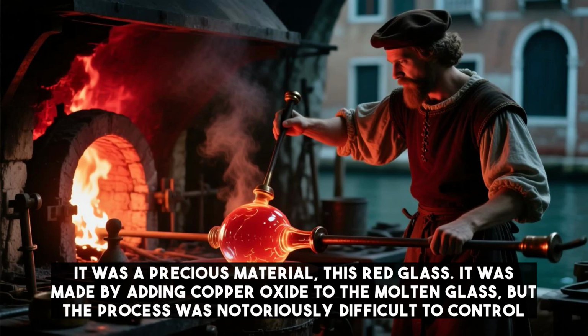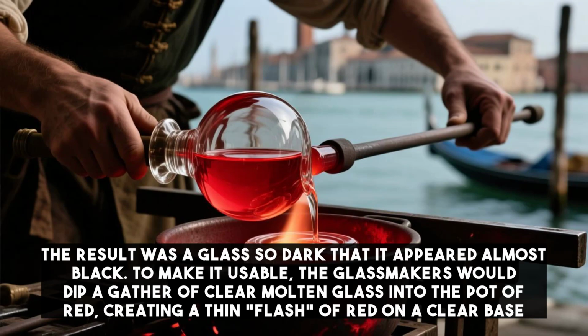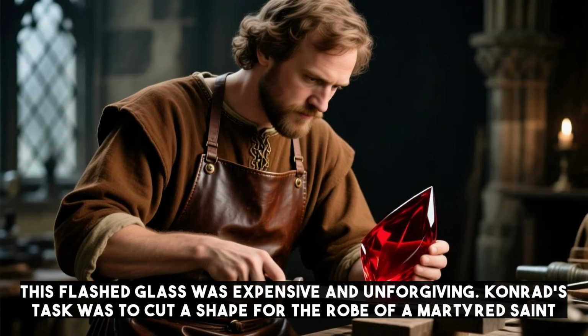It was a precious material, this red glass. It was made by adding copper oxide to the molten glass, but the process was notoriously difficult to control. The result was a glass so dark that it appeared almost black. To make it usable, the glassmakers would dip a gather of clear molten glass into the pot of red, creating a thin flash of red on a clear base. This flashed glass was expensive and unforgiving.